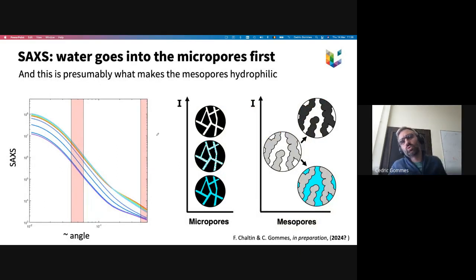So what you're seeing here is the small angle scattering pattern at one height and for various times. So we're going from red to grayish and then purple. Yeah? And so these are logarithmic scales. So really the signals are very strong. You see, you have a factor 10 increase and decrease of these things. So to really understand what happens there, you have to